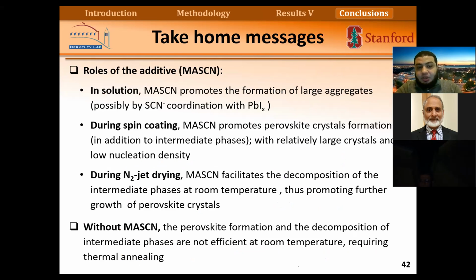As the take-home message about the role of the additive: in solution, it induces large aggregates, and during spin coating, because we have large aggregates, it tends to form larger crystals, and these larger crystals have lower nucleation density. And if we apply nitrogen, the additive helps to dissociate and decompose the intermediate phases and helps to grow the perovskite phase. If we don't have additives, the perovskite formation and dissociation doesn't happen efficiently at room temperature, because some of these intermediate phases are very stable at room temperature, so we need thermal annealing for these.